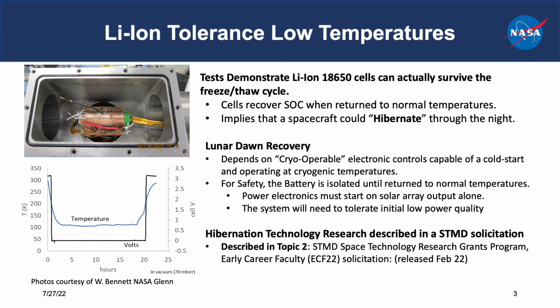So lithium-ion tolerance of low temperatures is the key. Tests have demonstrated that lithium-ion 18650 cells can actually survive the freeze-thaw cycle. Cells can recover their state of charge when they return to normal temperatures. Now, this implies that spacecraft could hibernate through the lunar night. The complicated part, of course, is the lunar dawn recovery.